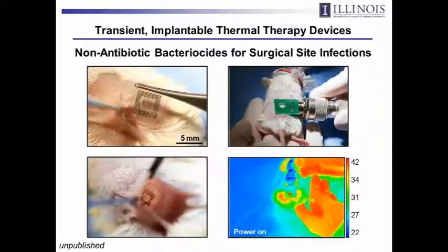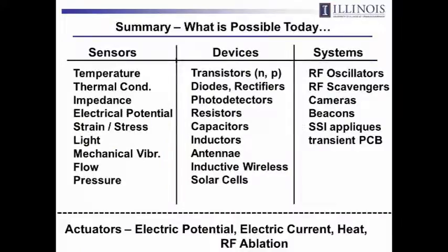But in this case, you really only need the device for a period of 2 weeks or so, because once a patient moves beyond that period, the incidence of infection is very, very small. So you'd like the device to naturally go away after 2 weeks to eliminate that unnecessary device load, and that's what this component is designed to do. You can see it on an IR camera. You can heat up well-defined locations under the skin, and then this thing dissolves over time. About three weeks, it's gone essentially. So that would be one.